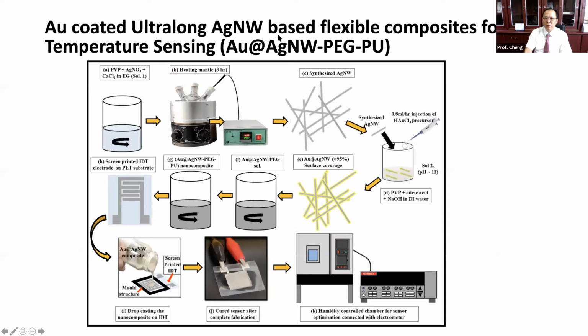So for the first part, the temperature sensing, we try to use a gold-coated ultra-long silver nanowire based flexible composite for the temperature sensing. So in our lab, we can synthesize the silver nanowire by ourselves. But because this is a wearable device, we need to attach it to your skin for a long time. So you know silver is very sensitive to oxidation. So we try to develop a silver nanowire without any oxidation.